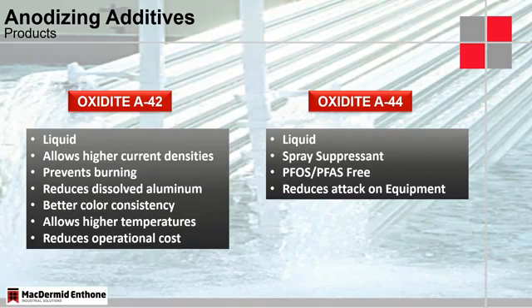So, some of the additives we were talking about earlier. The product we mainly sell for anodizing, especially type 2 anodizing and some type 3 anodizing applications, is the Oxidite A42. That's a liquid additive that really prevents the burning. It reduces the dissolution of the aluminum oxide layer, and therefore gives us higher thicknesses in shorter plating times or anodizing times. And therefore it increases the efficiency of an anodizing line significantly.